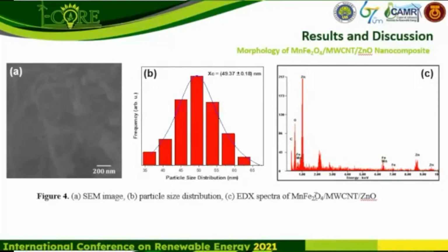It is caused by the modification of multiwalled carbon nanotubes, which results in a carboxylate surface defect and then becomes the attachment site for nanoparticles. Moreover, the addition of zinc oxide resulted in more particles covering the multiwalled carbon nanotubes. The possible mechanism to explain it is that multiwalled carbon nanotubes have a strong absorption tendency, which has been confirmed from the FTIR result, where it shows a strong absorption between zinc and carbon functional groups.